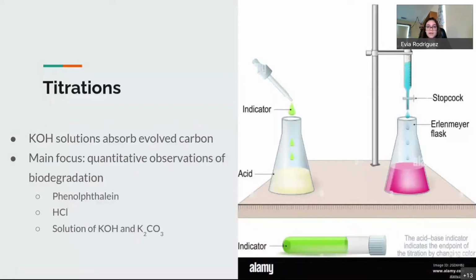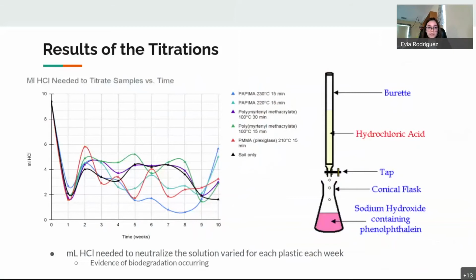Here's my raw data. It's a bit messy. However, the main thing I wanted to point out here, this is the graph of how much hydrochloric acid I needed to titrate the solutions in each of the jars to the equivalence point. And the main thing I wanted to point out is that there is evidence of biodegradation occurring, because if there wasn't, all of the lines here would look like the black line. Since each line is each jar, and each jar contains a different plastic sample, if there's no biodegradation, then all of the jars would be releasing the same amount of carbon, and therefore they'd all look the same. However, they don't, so there's evidence of biodegradation.